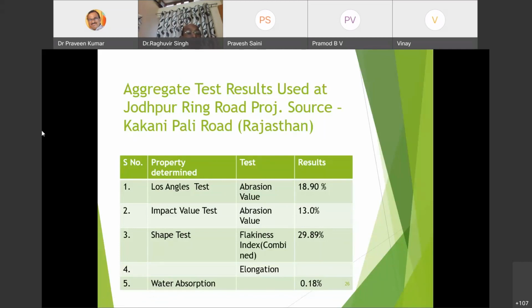The Los Angeles test was conducted in our in-house site laboratory, as well as in a third-party NABL accredited laboratory. The abrasion value of the aggregate was found to be 18.90%. The maximum permissible Los Angeles value is 35 for DBM cases. Impact value was found to be 13.01, where the limit is 25 for BC cases and 27% for DBM cases.